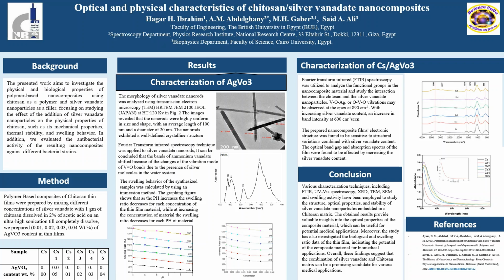Variable mass fractions of the synthesized nanoparticles were added to the virgin polymeric samples. Their structure and characteristics were investigated using optical and physical characterization techniques. The morphology of silver vanadate nanorods was analyzed using transmission electron microscopy. The images revealed that the nanorods were highly uniform in size and shape, with an average length of 100 nanometers and a diameter of 20 nanometers. They exhibited a well-defined crystalline structure.